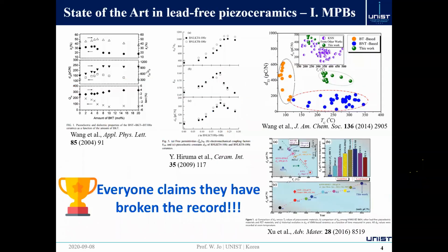If you look through the literature, you can see a lot of record-breaking achievements. Most of the papers are claiming that they have a wonderful material developed, for example, d33-wise, achieving a certain value which has never been achieved before. And people already know that if they want a better piezoelectric coefficient, they need to sacrifice the Curie temperature.